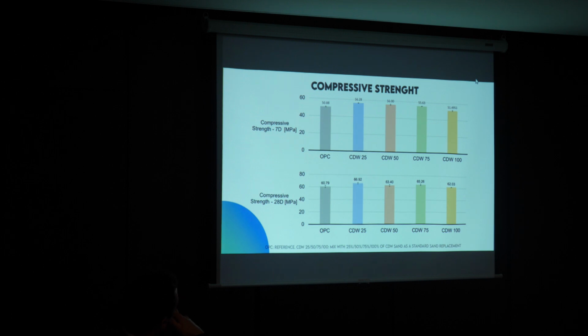Regarding the compressive strength, improvements were obtained in both cases, from 7 days and 28 days, arriving also in this case at an improvement of 6 to 10%. And there was also a slight improvement even when the standard sand was completely substituted.